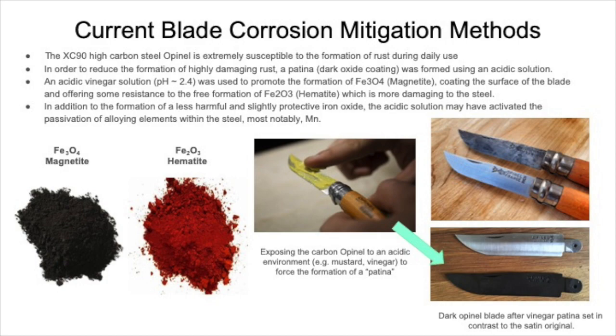For this Opinel, it was placed into a vinegar solution with an estimated pH of 2.4, which promoted the formation of Fe3O4, the mineral magnetite, coating the surface in a powdery, almost black coating. Through a slight passivation effect, this offsets the formation of much more damaging Fe2O3, the mineral hematite, the classic rusty red color, which experiences a significant volume change resulting in the flaking and continual deterioration of the metal.